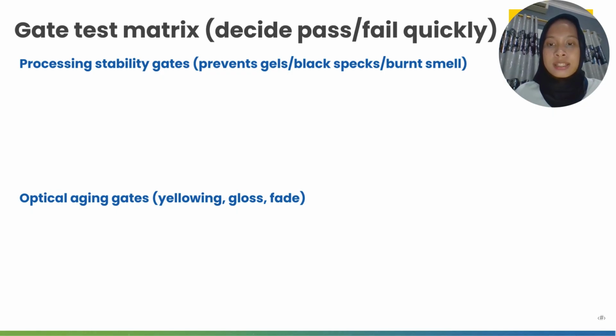The second one is melt flow or viscosity drift. The criteria is minimal drift after the controlled reheat or extrusion, and it's diagnosed by thermal or oxidative stability. For film gel count or black speck count, the criteria is below visual threshold for window clarity, and it's diagnosed by degradation, contamination, and poor filtration.